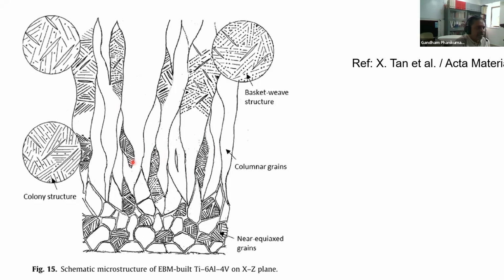And depending upon our applications, we have specific preference for some of these microstructures. So if you see the columnar growth, the grain boundaries are vertical, which means that you may prefer them in applications where they are along the height of a blade, so that the stresses acting on a blade would not lead to any failure because there are no horizontal boundaries, it's only vertical boundaries.